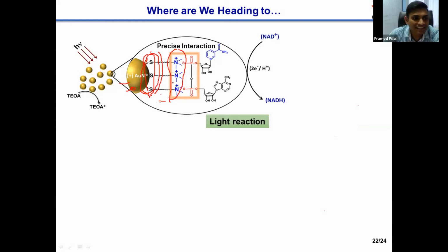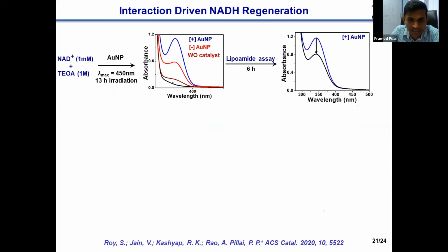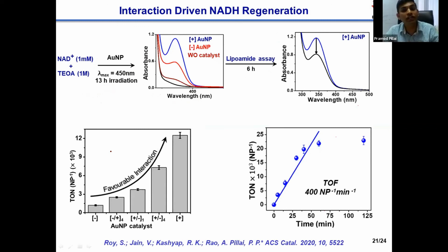Now, what I was very keen on was knowing how do you calculate the turnover number per nanoparticle? We have done that for metal nanoparticles. What we do is we know the concentration of the nanoparticle that we are taking. And that is by absorption or by weight? It is by multiple techniques. One, we take the absorption, and then we take the TEM, and then we digest the nanoparticle to know the amount of gold ions. And by the knowledge of the size of the nanoparticle, we can calculate how many gold atoms will be there in a single nanoparticle. And from that, we calculate the concentration of the nanoparticle. All right, the turnover frequency becomes a straightforward calculation. Right, the trick here is to estimate the concentration of nanoparticles.